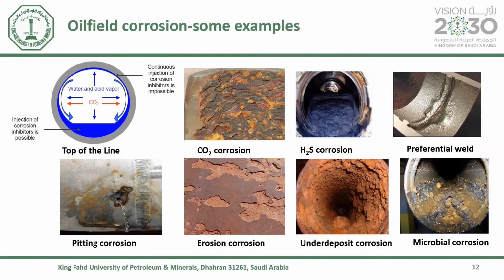General corrosion is not really very important, but severe damage, localized corrosion due to pitting, is very difficult to mitigate. Erosion corrosion is due to wear or flow. Under deposit corrosion forms due to formation of scales on the pipe. And then the microbial corrosion, which is very, very important too, due to reduction of sulfate to sulfur by sulfate reducing bacteria.